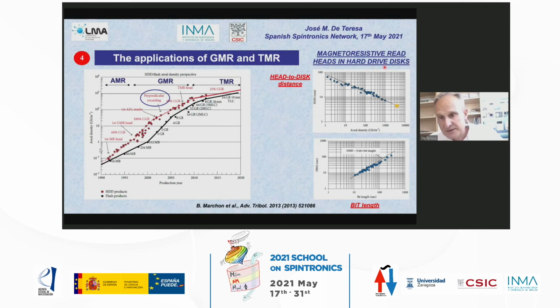Regarding the magnetoresistive read heads in hard drive disks, that is probably the most known application of GMR and TMR, we have seen a strong evolution of the technology with time. So the first magnetoresistive heads were introduced around 1991, and the technology was anisotropic magnetoresistance. The magnetoresistance effect was, as I mentioned before, just a few %, but it was enough in order to read the information for the areal densities that were taking place at that time, which was around 0.1 gigabit per square inch.